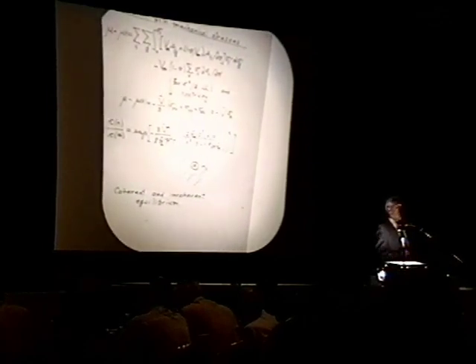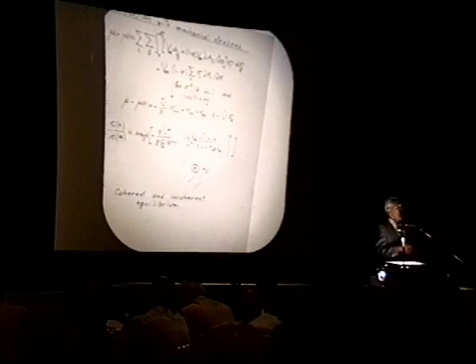And this is the basic reason why, when you try to establish a phase diagram in metal-hydrogen systems, you have hysteresis. Because in no case do you have perfect coherence or perfect incoherence. You always have a residual dislocation distribution and therefore a higher free energy situation.